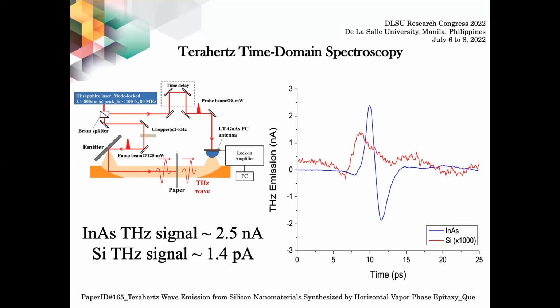Although the emitted terahertz signal from the silicon nanowire sample is still far from that of indium arsenide, we have shown that terahertz emitters can also be synthesized using the horizontal vapor phase epitaxy method.